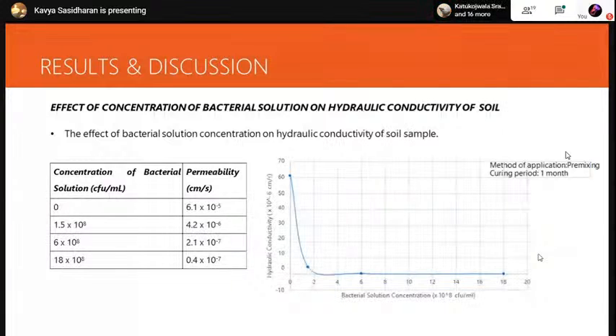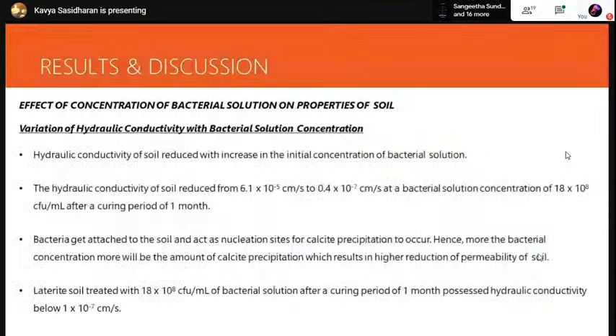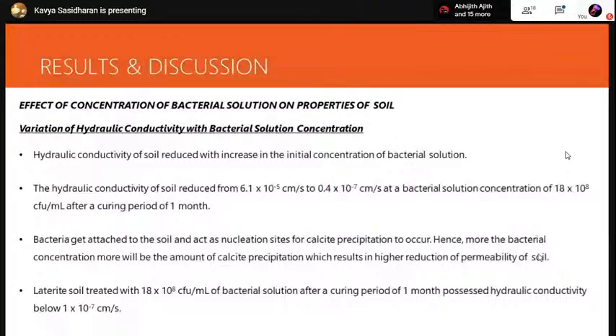Next is the effect of concentration of bacterial solution on hydraulic conductivity of soil. The concentration of bacterial solution was varied as shown in the table, and the permeability goes on reducing from the order of 10 raised to minus 5 centimeter per second to 10 raised to minus 7 centimeter per second. This is because there is obviously a reduction of permeability due to calcium precipitation occurring within the soil pores, and it is observed that laterite soil treated with a bacterial concentration of 18 into 10 raised to 8 CFU per milliliter, provided a curing period of 1 month, possessed a hydraulic conductivity below 1 into 10 raised to minus 7 centimeter per second, which is the criterion given by EPA.